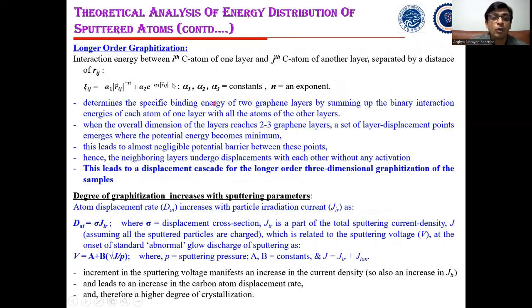Now also we see that when we increase the voltage, or when we continue sputtering, the ordering of the graphitization is increasing. This is because some potential energy minimum is created that creates a cascading effect for longer-order three-dimensional graphitization of the samples. Also, with an increase in the sputtering parameter, the structural ordering is increasing, which can also be theoretically analyzed.